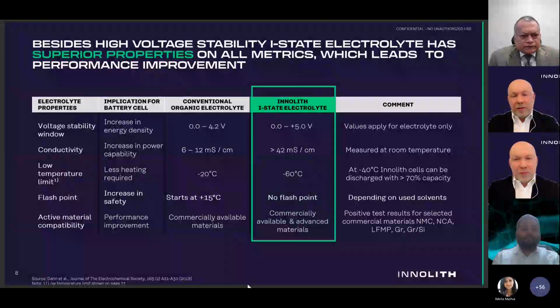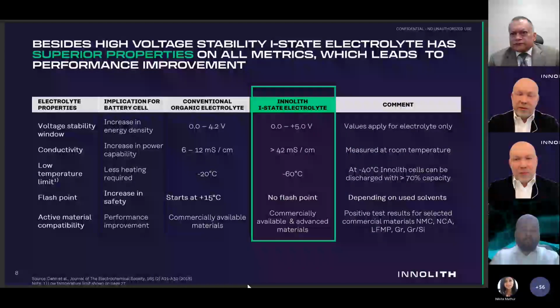And last but not least, with organic electrolytes today, one can work only with commercially available materials, and as I've mentioned earlier, not with the new materials that have been developed, which require higher voltages, like many of the combinations with manganese, where the content of nickel, which is expensive and also relatively hard to source, is replaced. Replacement of nickel with manganese is one of the future opportunities in the industry. There one needs higher voltage in the system, and conventional electrolyte is an obstacle. We can move to the next one, please.